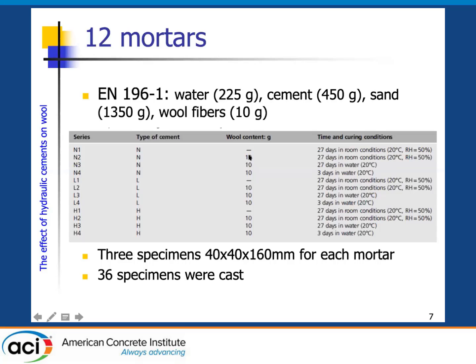However, in this case, we introduced 10 grams of wool, which is more or less 1% in volume of fibers. The third series, the 3H series, is related to the same content of wool and cement, but in this case, we stored the specimens after casting 27 days in water. And finally, in the 4H series, we cured the specimens 3 days in water, 1 day after casting. So in total, we have 12 series. For each series, we cast 3 specimens. So in total, we tested 36 specimens in 3-point bending.